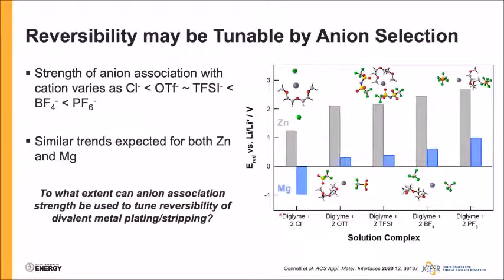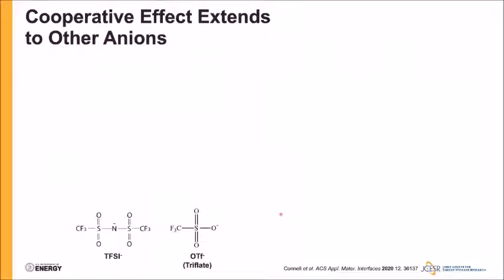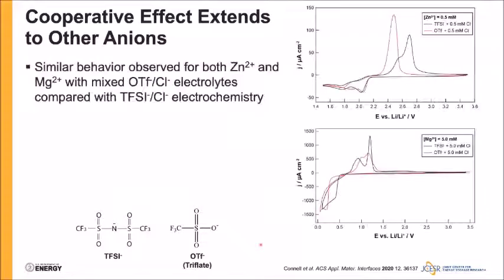So we want to know, to what extent can anion association strength really be used to tune the reversibility of metal plating and stripping? And so we begin by exploring a sort of chemically similar anion to TFSI, this triflate anion shown here schematically on the bottom left. And what we see is that for both zinc and magnesium, we see very similar behavior for both the mixed TFSI chloride and triflate chloride systems, where the magnesium more or less looks identical, where we see 2 oxidation features and 2 reduction features in direct analogy to what we saw with the zinc system.